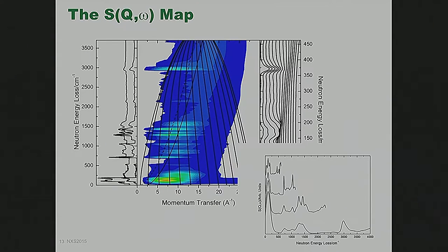There's another interesting effect when you measure in VISION: the instrument is essentially constant. You cannot change the instrument. Whereas with direct geometry instrumentation, when you change your incident energy, you really have a different instrument with a different resolution. Because the resolution in VISION is always constant, if you measure something and then measure something else, and one has twice as much as the other, you are always sure that you have twice as much material, twice as much scattering, which you don't have in the other ones, okay?